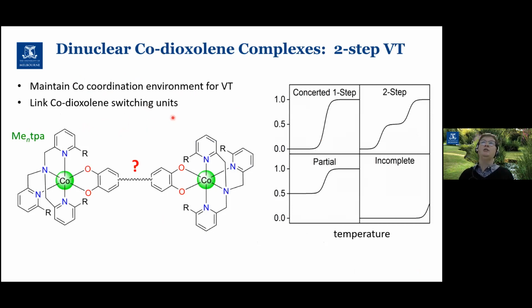Okay, so we set out to do this quite a while ago now. So obviously we were thinking, how do we do this? We want a dinuclear cobalt complex that'll do this two-step VT transition. So we set up our cobalt dinuclear complexes. We use that nice family of TPA ancillary ligands that we can tune very nicely to control the VT switching at each cobalt center. We wanted to have dioxolenes there. So the key was really how we actually linked those two dioxolene units together.